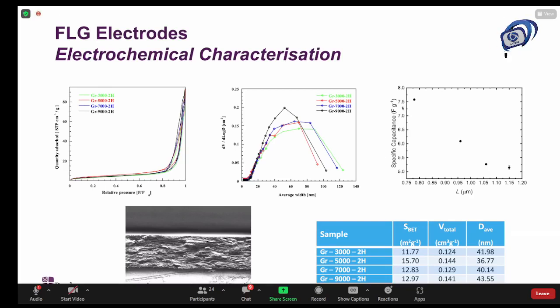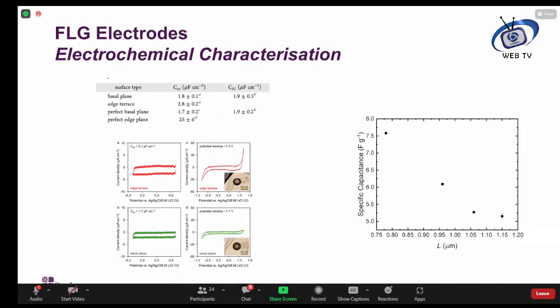But you can see over here on the right, there's something very interesting. The specific capacitance increases as the linear dimensions of the few layer graphene platelets decreases. And we can understand that by appealing to some work by Velitsky et al. from a couple of years ago, who looked at the capacitance of micro areas on the basal plane and on the edges of graphite, and they found that a perfect edge plane on graphite had a much higher specific capacitance than the basal plane. So obviously, to have an active additive that both helps the conduction of an electrode made of another material and actually contributes towards the specific capacitance, we want to use small platelets.